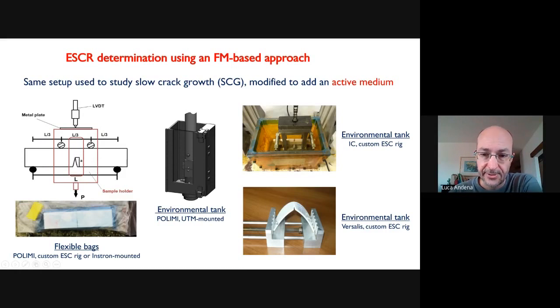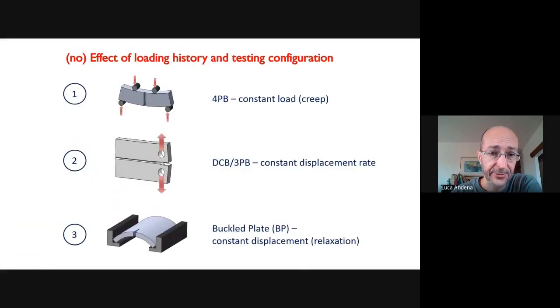Okay, this is a strange configuration. I will tell more about that later on, because the first point that I would like to address is that I mentioned that a defect of these industrial standards is that they're geometry dependent. So the first thing is to assess whether the fracture mechanics approach can instead be geometry independent, and also to check the influence of the loading history.